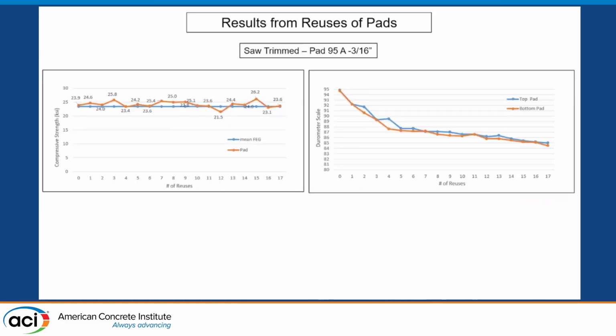And so another thing that we wanted to see was, can these pads be reused? In testing, for most of this data, we were just using one pad, and then we get another one and put it in there. So we conducted some reuse tests, and we took a 95A 3/16 pad. In this case, all of the cylinders were saw trimmed. And we saw that over time, the pad was getting softer, going from a 95A 3/16 pad to around an 86A, let's say.